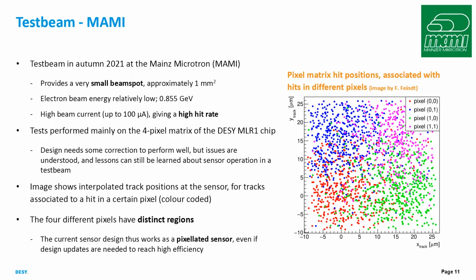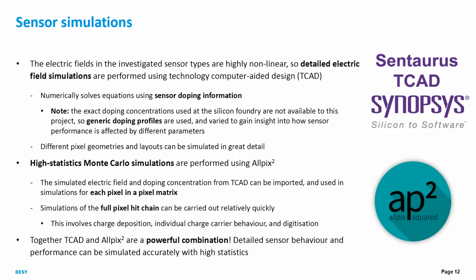This leads on to the sensor simulations. So the electric fields in our sensors are highly nonlinear, so we need detailed electric field simulations, and we do that by using TCAD, technology computer-aided design, specifically Sentaurus TCAD by Synopsys. And what this does is to numerically solve equations using sensor doping information. And important to note here is that the exact doping concentrations that the silicon foundry uses are not available to us, but we can use generic doping profiles and then vary them to gain insight into how sensor performance is affected by different parameters. So we can always do relative measurements at least, even if we don't have proper profiles.